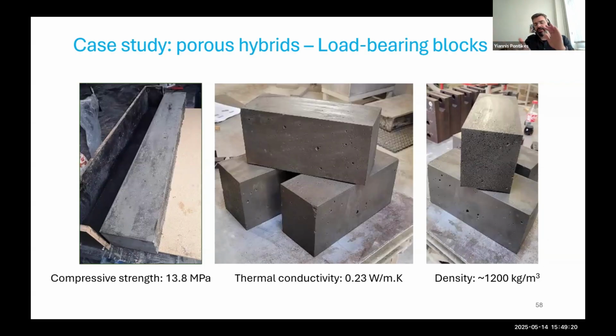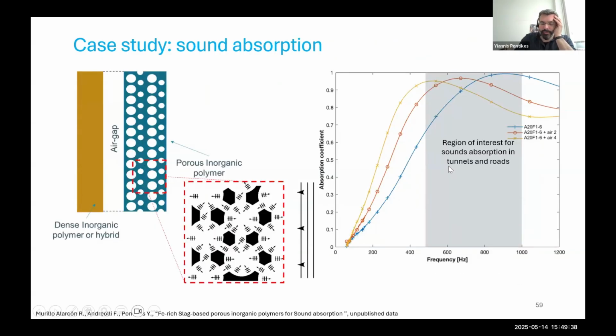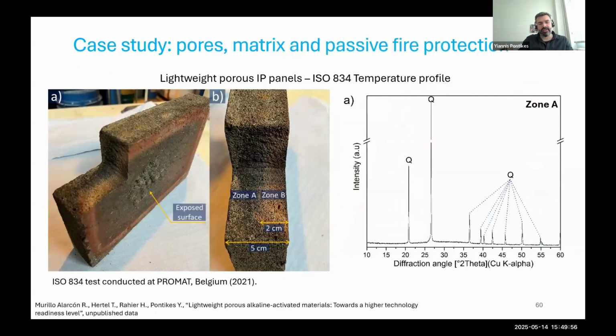You can do it in different ways, by foaming agents or by surfactants or a combination of the two. And we made a wall. So I think we made more than 200 bricks, and they were big. They were not small bricks, because we also, or the industry, wanted to see eventually the performance in a wall structure. If you have porosity, you can think of thermal insulation, you can think of sound absorption. So it's also a wall that will be probably creating quieter rooms. And depending on, again, on the pore size distribution, you have a different performance also from the acoustic side, which is, again, interesting.